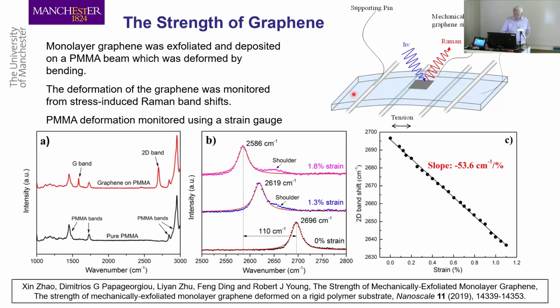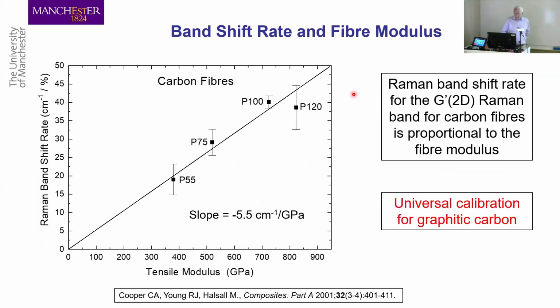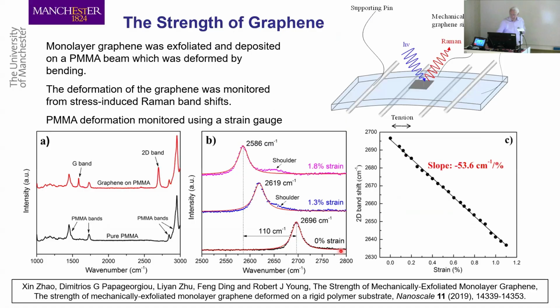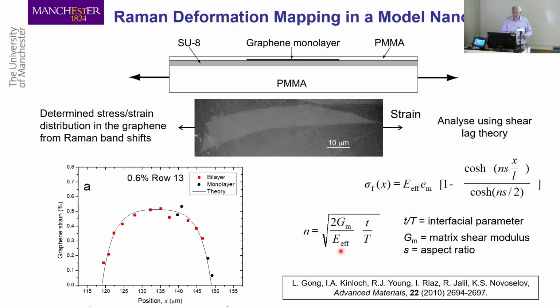And we go back to our previous plot here, our carbon fiber calibration. A slope of -55 is off the top here. It's about up here. And it corresponds to a modulus of about 1,000 gigapascals. So it means that the modulus of this material is 1,000 gigapascals. So that's what people found mechanically. That's what we found with Raman. So that's the first thing we've got.